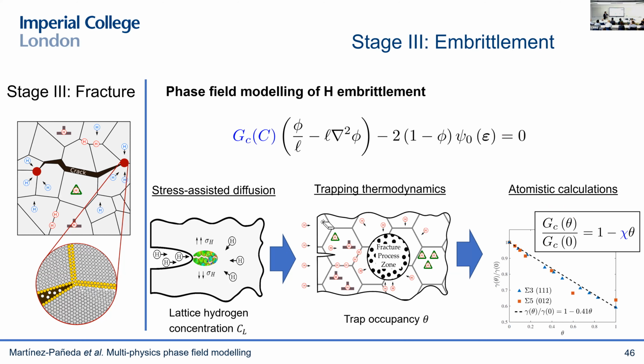And incorporating this into phase field is straightforward because we are solving the hydrogen diffusion problem, so we know how much hydrogen we have, where and when. We can use trapping thermodynamics to determine, for that hydrogen concentration, how the hydrogen is going to be distributed in the microstructure, in my grain boundaries, for example. And then we just need to go to this DFT calculation that we run once in our lifetime offline, and then we can quantify how much the hydrogen reduces the fracture energy.